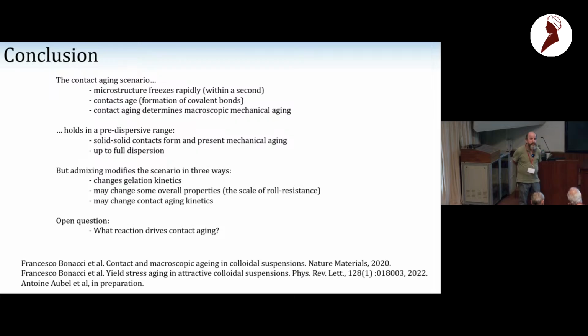Absolutely. For the rigidity, it's pretty clear that the relation between the contact stiffness and the macroscopic modulus is almost evident. If you look at the linear response and write your energy only in terms of bending, you immediately see that G prime should be proportional to the flexural stiffness. This is quite easy to derive. The relation between the yield stress and the rolling limit is much more complicated because during yielding, lots of things happen.